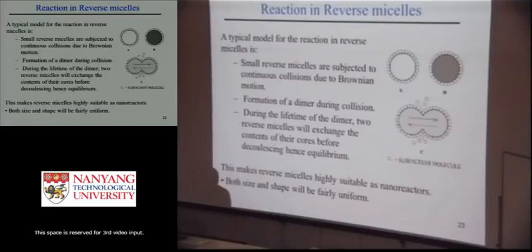Okay. Now similarly, you can make another microemulsion. I dissolve B into a small amount of water. Then I put this water into the oil, then add the surfactant again, and magnetically stir it for some time. You get another batch of microemulsion. In order for the reaction to take place, you simply pour microemulsion B into microemulsion A.